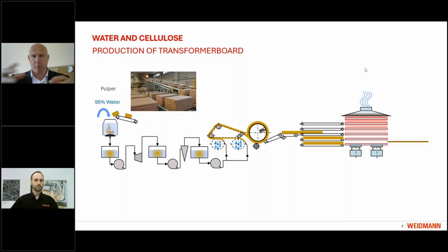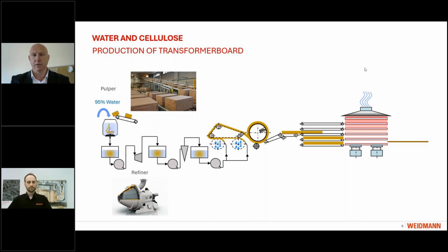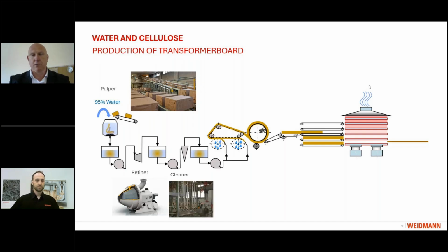then we need to put it to the pulper, to put water and to put pulp and then mixing. So in that stage, we apply about 90%, 95% of water and only 5% of pulp. So then all this mixture goes through the paper making process. We use refining to create some special surface of the fibers and to increase the connection. Then we need to clean this mass and we use the cleaner for that. Then we make a formation.